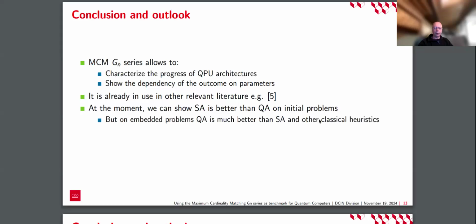But when we take into account the fact that we have to embed our problem because of the sparsity of the architecture, then in this case, quantum annealing is much better than simulated annealing. And in any case, it has the advantage in most of the cases that it gives a good enough solution in a really short time. Typically, in less than a few milliseconds, you have a good number of samples, typically 1,000 samples, for your possible solution of the problem. And within that, usually the best solution is not so bad.